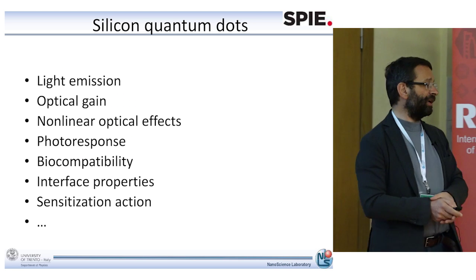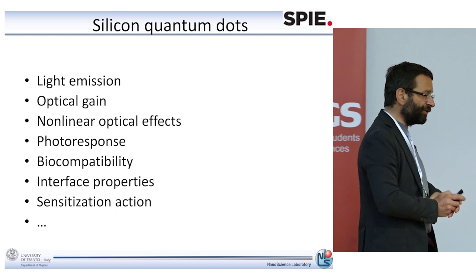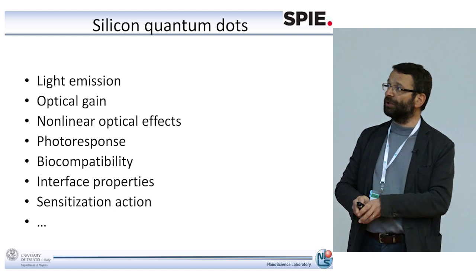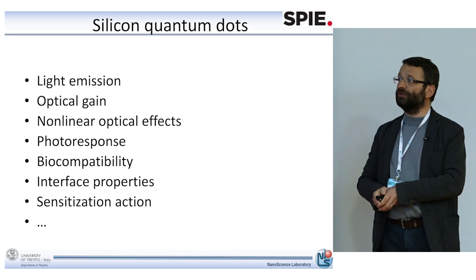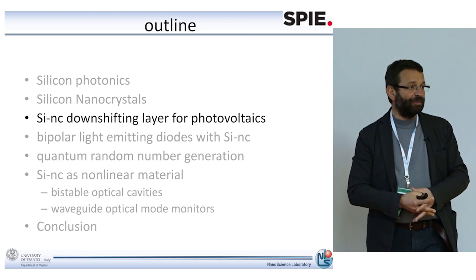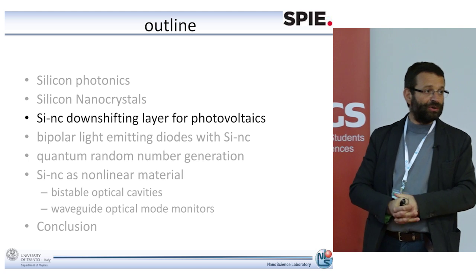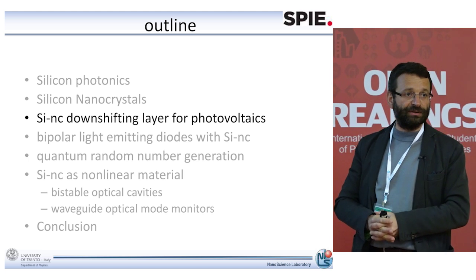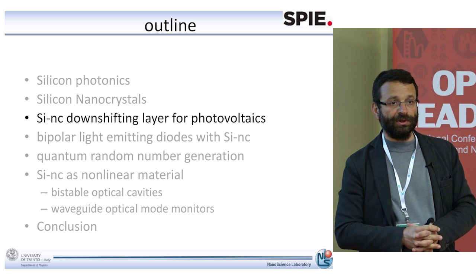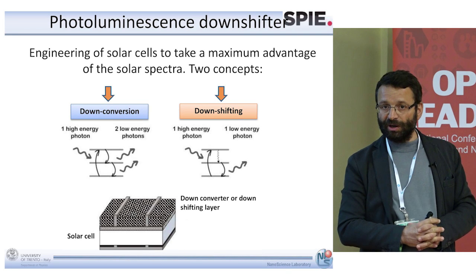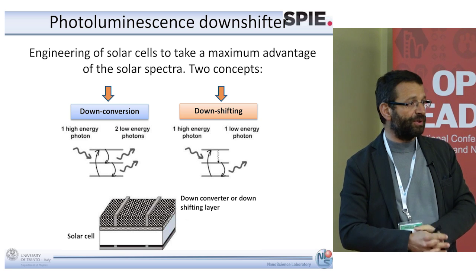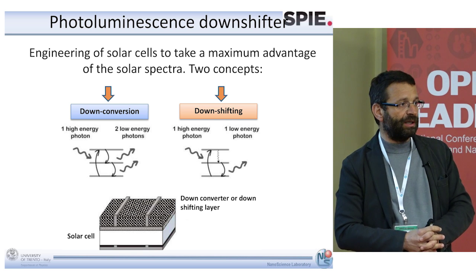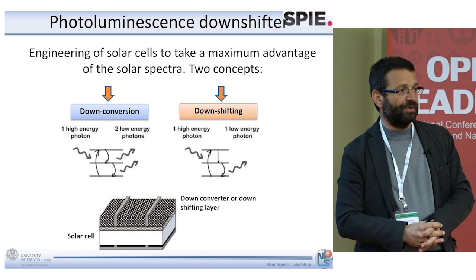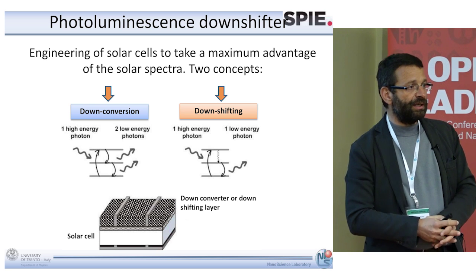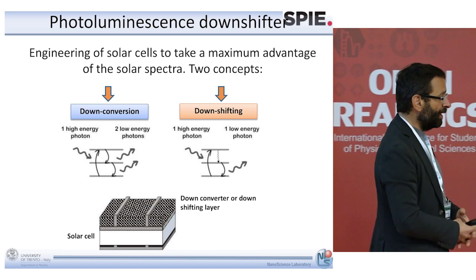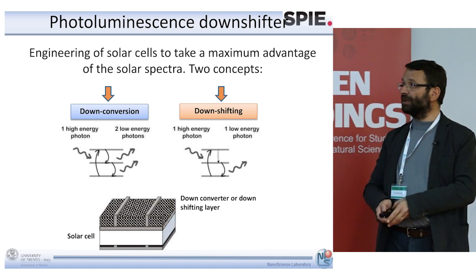Good. But this is not the only interesting application for the silicon nanocrystal, not only the gain. So I want to show you a few other kinds of application. The first one, since I saw today a few papers on photovoltaics, I want to show you what we can do with silicon nanocrystals in order to improve silicon photovoltaics. One of the problems with silicon photovoltaics is that we consume a lot of sun power in internal relaxation, so in heating the cell. So here the idea is to use the silicon nanocrystals to improve the efficiency of the silicon solar cell.